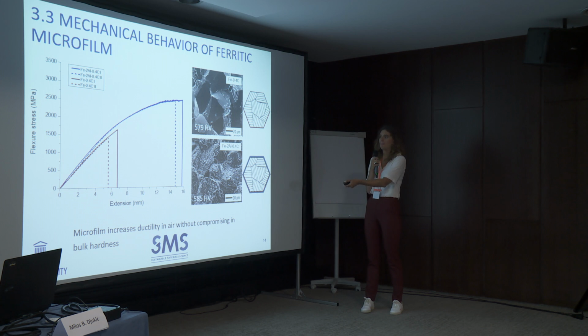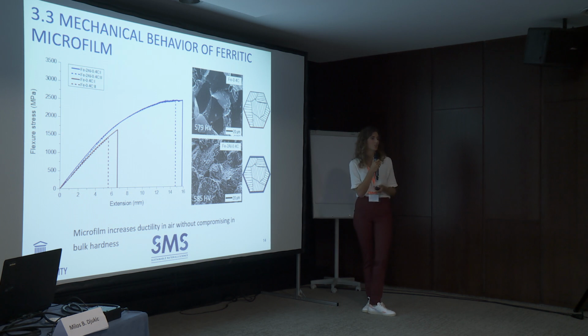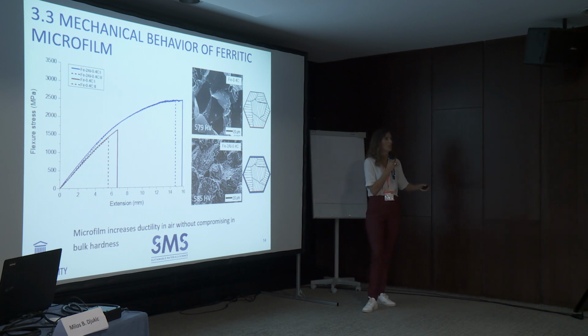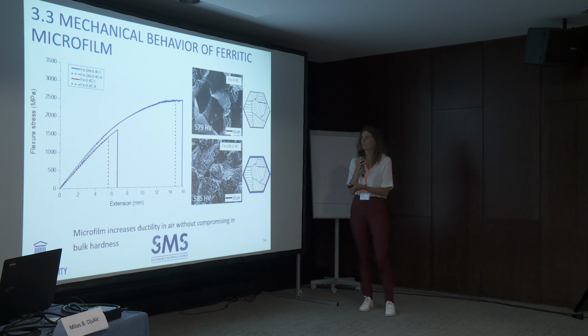But it really breaks very soon without this ferritic microfilm, and when we add aluminium and create this ferritic microfilm, we really can sustain much, much higher extension values than without it. We can also see this in the fracture surface. Without aluminium, we have a purely intergranular fracture surface, but when we add aluminium, you really can see microvoids on top of these intergranular features, and this really indicates that fracture occurs along this ferritic microfilm.